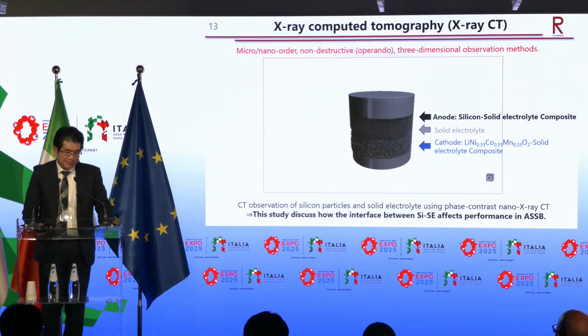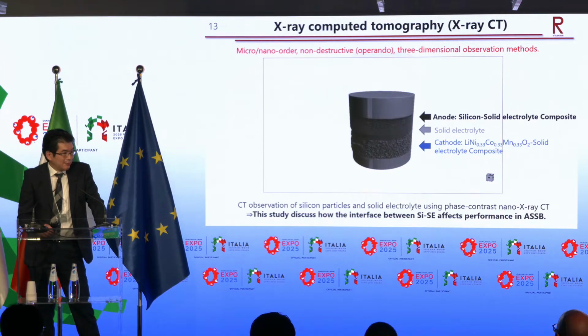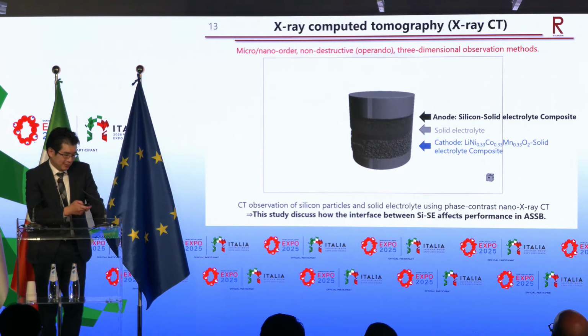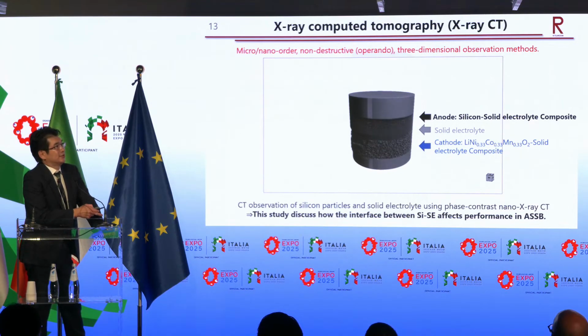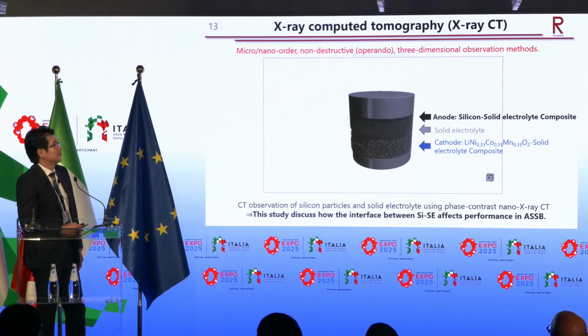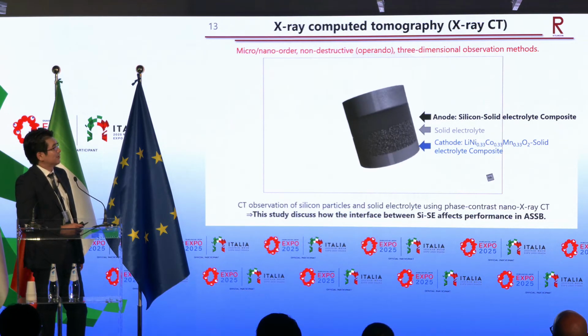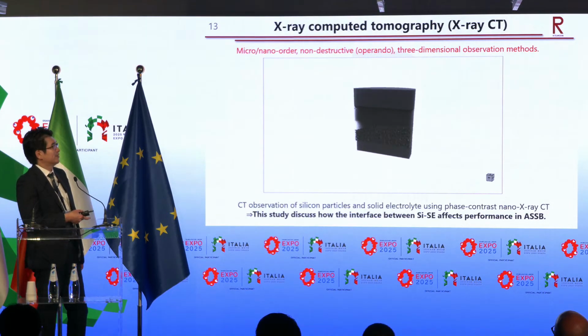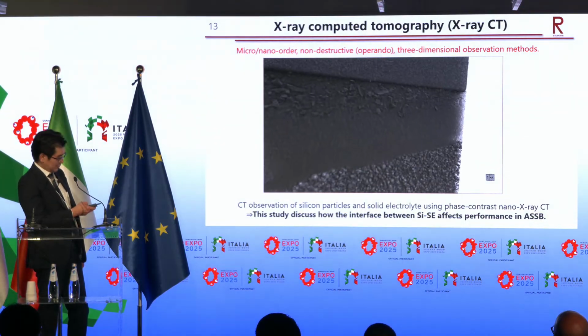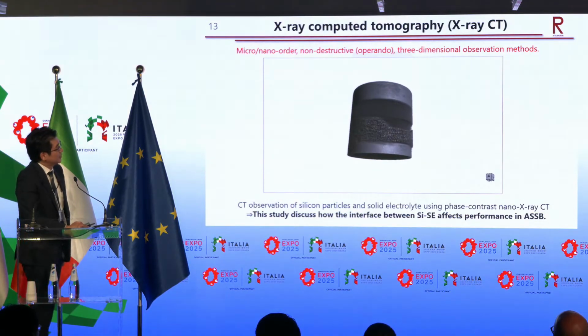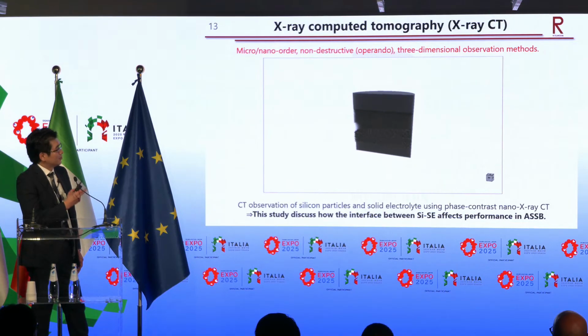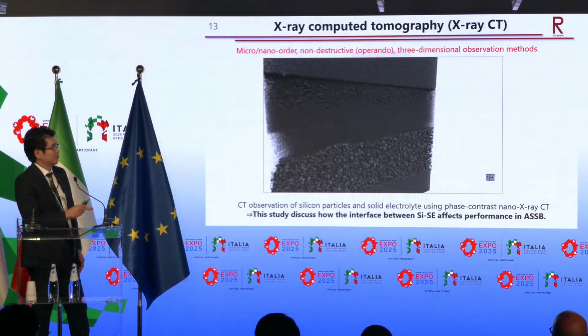However, we have many disadvantages of all solid state battery. It is easy to imagine the poor contact between materials, like electrode active material and electrolyte. So to analyze the contact state of all solid state battery, we apply X-ray CT. X-ray CT, maybe you know, is very powerful to detect morphological change. And if we use synchrotron X-ray, we can directly detect morphological change during charge discharge. And this is the silicon active material here. So we study the contact state between the silicon active material and the electrolyte during charge discharge.